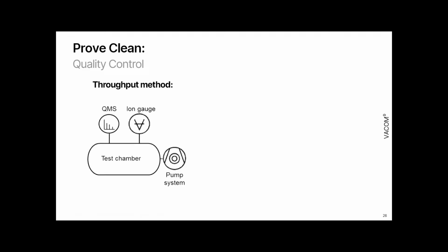When we think about RGA measurements, we have a couple of different methods that we use, which depend on the components themselves, right? So we have the so-called throughput method, which is a continuous measurement technique, right? You're pumping down continuously, you're measuring continuously. The spectrum that you get in your RGA is dominated by surface adsorbates, mainly water and hydrocarbons. The only problem with this technique is if you have very small samples or very clean samples, you can't actually detect anything in your RGA system because it will just disappear in the background of your chamber, right? So your chamber, you would first measure your empty chamber. That gives you a background measurement. Then you put the part in, and then you can deduct the two spectra from each other.